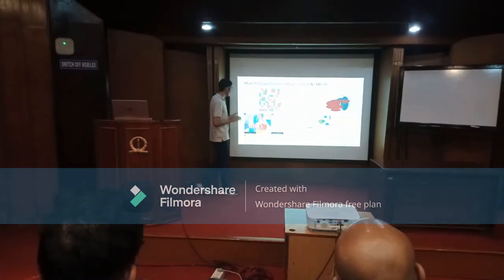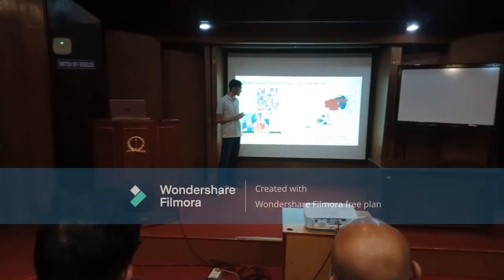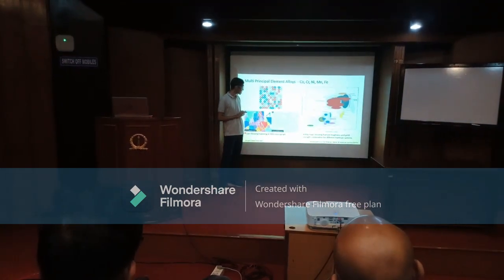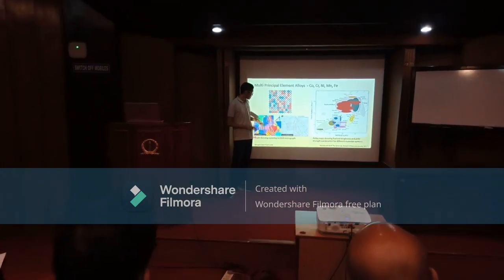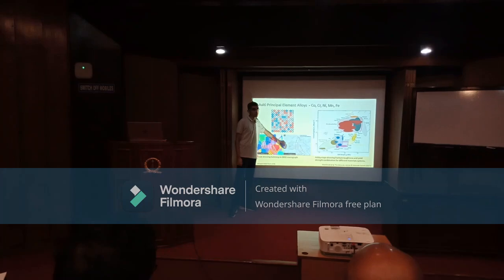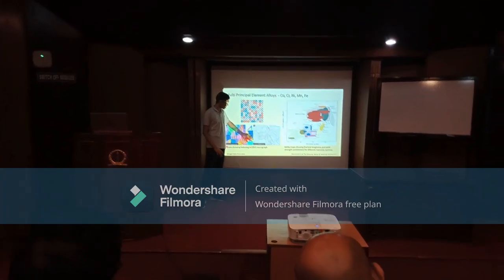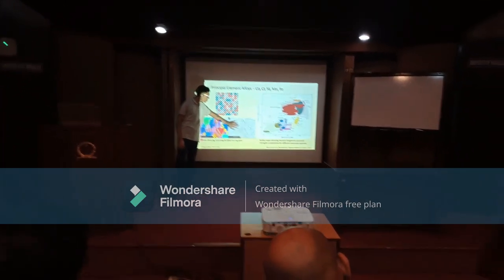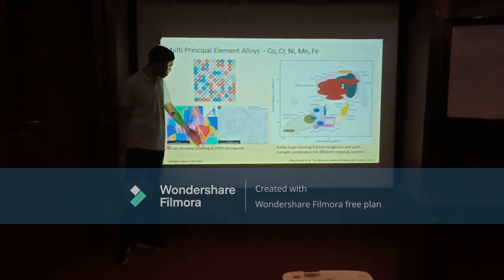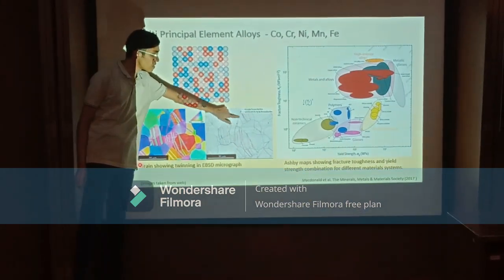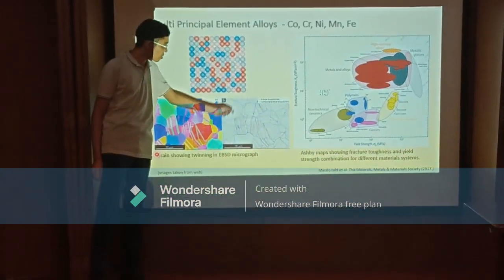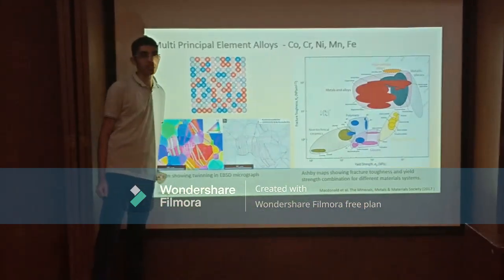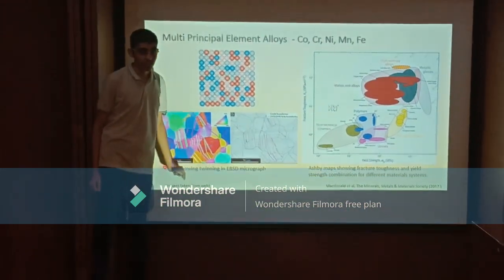Another reason is twinning phenomena, which happens in case of these alloys. So in these alloys, what we observe is, if we look at this particular micrograph, this shows you an image of what the metal looks like at a very high magnification. So we have different grain boundaries. These are different grains of the metal, but along with these, we have these stripes. So these stripes are called twins.